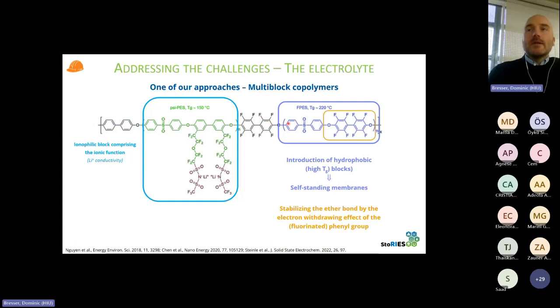It plays a very important role. I mean, you can synthesize the molecule also without the fluorine here in the backbone. And so I mentioned already that it increases the electron withdrawing effect here on the ether type oxygen, right? In fact, if you synthesize the same molecule without the fluorine here, what you observe is that the electrochemical stability towards oxidation is decreasing, because the electron withdrawing effect of this perfluorinated phenyl compared to the pure phenyl, so to say, is much higher. So the electron density here in the oxygen is higher if there's no fluorine in here, meaning that it's more easily oxidized. So you see this in terms of electrochemistry towards oxidation.